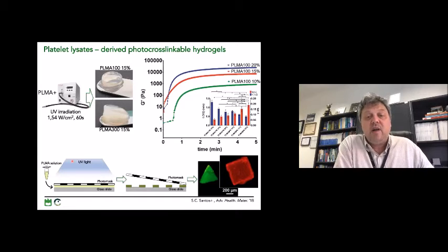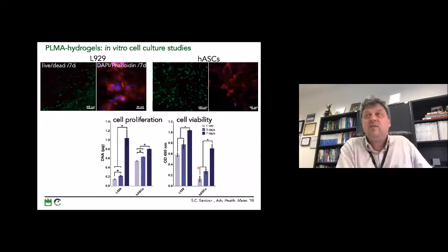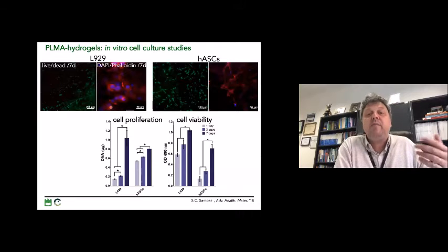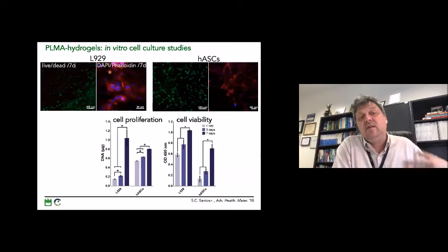So the photopolymerization may be performed through photomasks that will activate the PLMA solution that is below the photomasks only in the regions that allow the passage of light. This spatial control of the cross-linking allows us to form hydrogels with highly tunable geometry and size, which can be very interesting for some applications. What is also important is that the photopolymerization can be performed in the presence of cells. So we can really include cells such as L929 or adipose-derived stem cells inside the precursor, and upon irradiation, they will be fixed in 3D.